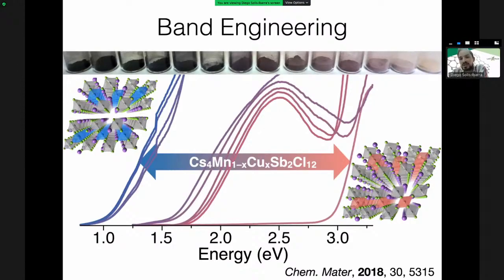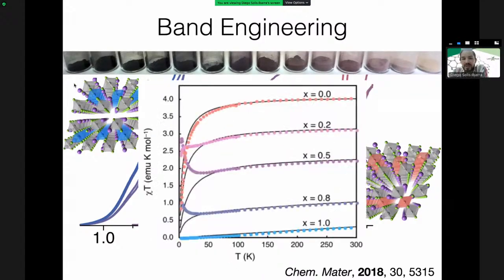So you can see here that the manganese-only material has this pale pink color, the color traditional of manganese. And as you go to the copper-only material, you get the bandgap of 1 electron volt, and depending on the concentration, you get this plethora of different properties or different bandgaps. Of course, when you're talking about manganese and copper, you are also changing the magnetic behavior of this material, which is something that is really interesting to explore.